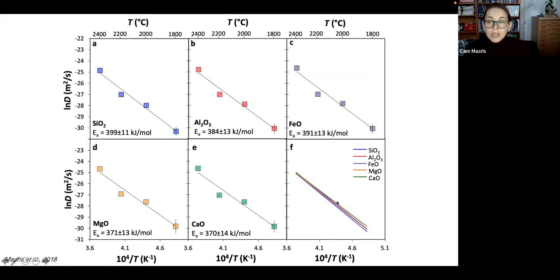And then here in the lower right, I've plotted all of these lines on top of each other on the same plot. And what you can see is that they are overlapping. They're very closely spaced, these lines. And that means that all of these components have very similar diffusivities, and as it also turns out, activation energies, which makes finding a unique solution to a given tektite's thermal history impossible.